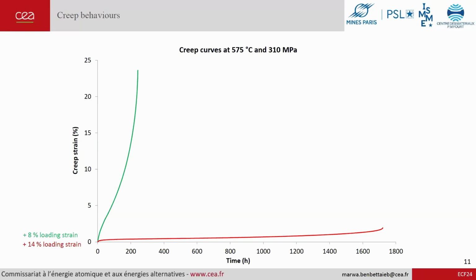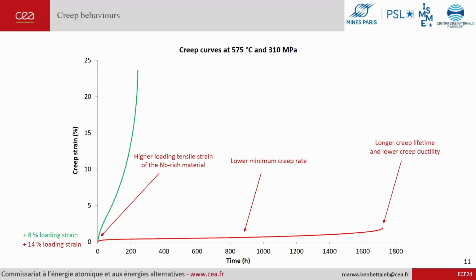So if we look at these curves, we can say that 14% strain was measured for the niobium-rich alloy at the loading phase of the test, against only 8% for the niobium-free alloy. And during creep, we can note visibly that the minimum creep rate is lower for the niobium-rich alloy, with a longer creep lifetime and a lower creep ductility during creep.